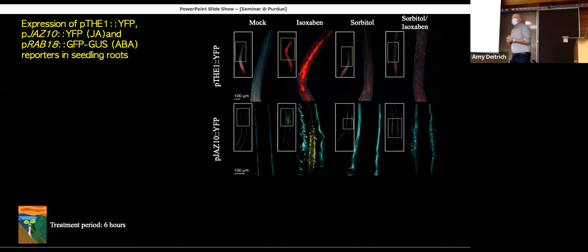Now, when you look at JAZ10, you see a very similar situation. Nothing in the mock-treated situation. If you give isoxaben, you get activation. It looks a bit like it's in the central cylinder and the surrounding cells a bit. If you treat with sorbitol, not much happening. If you do the double treatment, again, suppression. So in a way, it's following what you see for THE1.